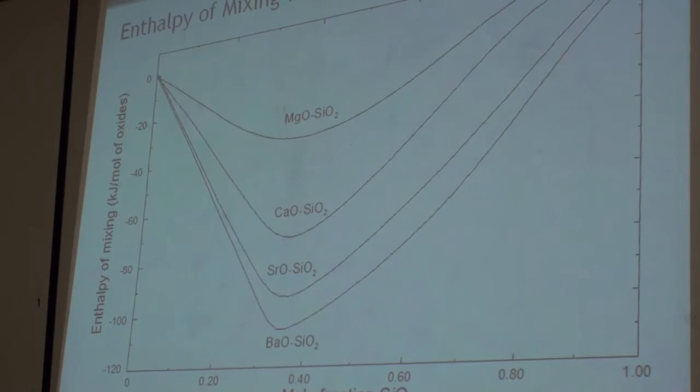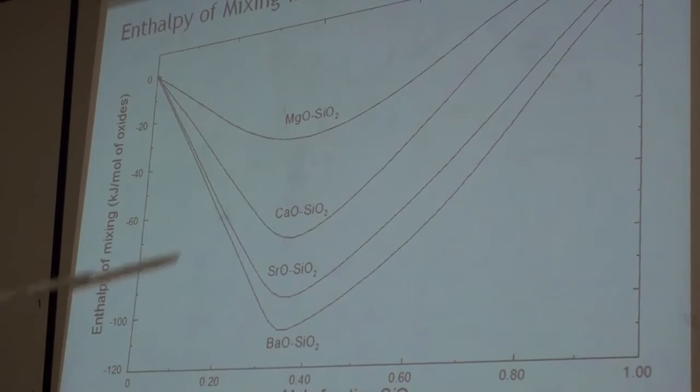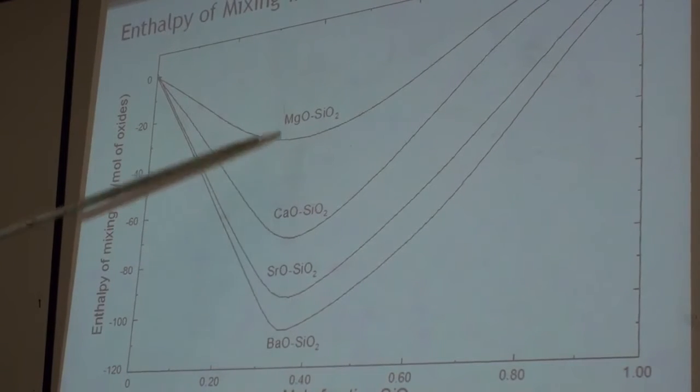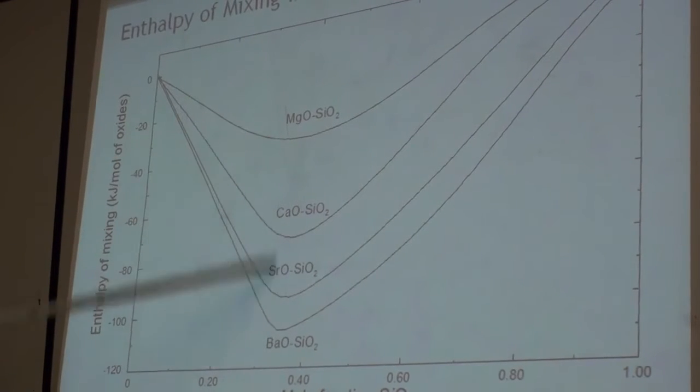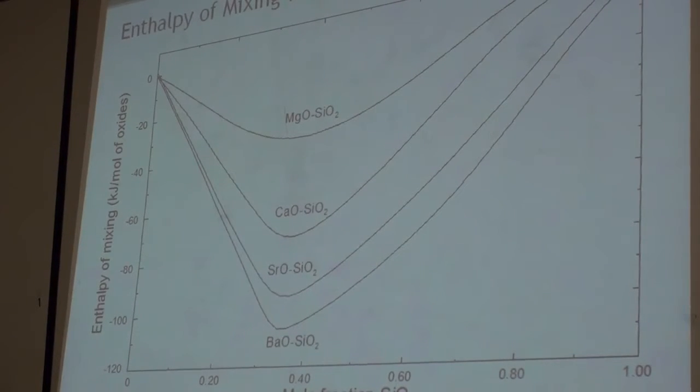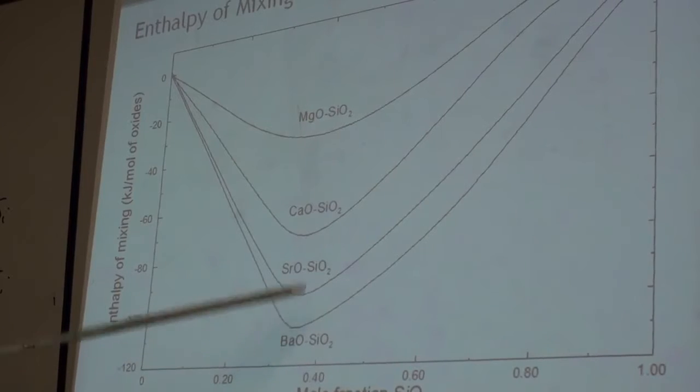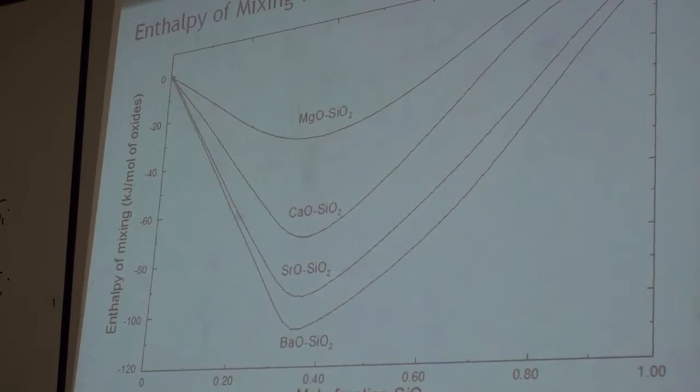It's the same order as I did, say, with the chlorides: lithium chloride, then going down, sodium, potassium, rubidium. It's the same thing as you go down the periodic table with magnesium, calcium, strontium, barium: you get stronger. As the cation barium is bigger than magnesium, you tend to have stronger complexing, a stronger tendency to break up, or the ceramists would say barium is a better network modifier than magnesium. It has a stronger tendency to break up the network, makes it more ionic.